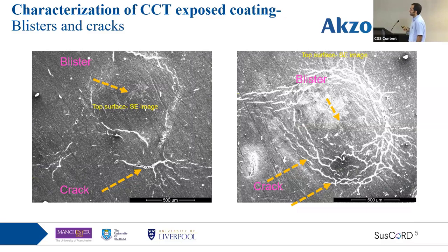This is the last slide. The other thing I wanted to show is that when the blister forms, we see that cracks start to form around it, as we also observed in the previous results. But when the blister grows, more cracks start to form, and not only around it, which may lead to the detachment of the coating on the blister eventually. But the crack seems to deviate and move out and further damage the coating, and continue this way. That may be the reason that we get a complete removal of the coating on the samples which were exposed for 6 months to the environment.